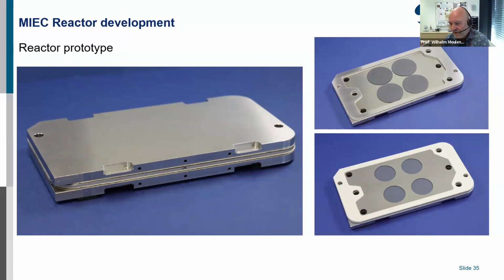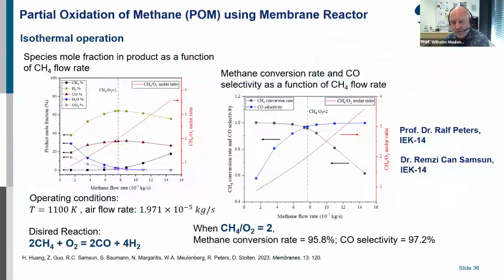But people who are working on stacking, you know, there are always some problems, sometimes with the sealing or sometimes the membrane cracks or other problems which can occur. And that is what we have to take now into account, how to operate such a stack for a long time. We already managed it for SOFC. We operated one stack with an aging rate of 0.8% per 1,000 hours, up to 100,000 hours. So that means more than 10 years, and that is demonstrated, and that is what we also have to target here in the next year to demonstrate that this partial oxidation of methane is working. So I'm a materials guy, but we have also some colleagues in other institutes in IEK-14.